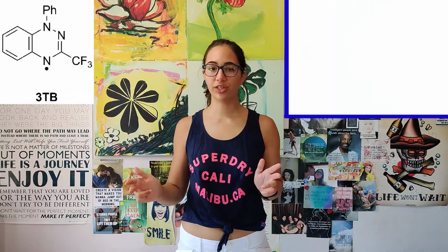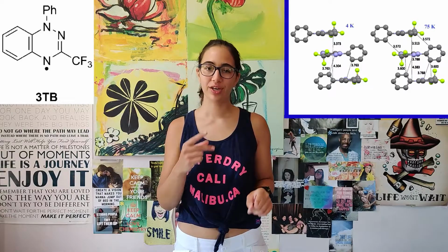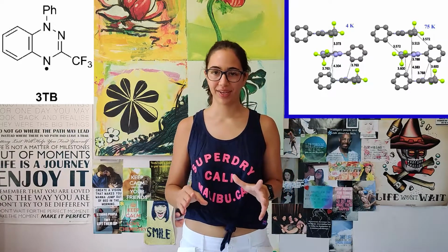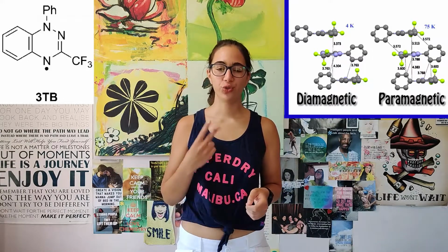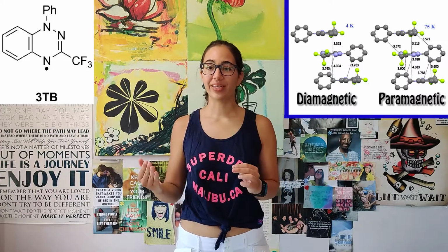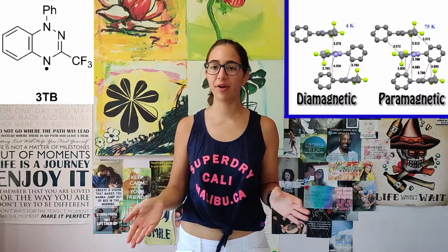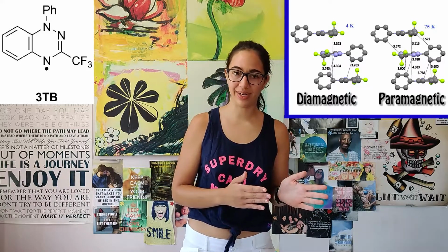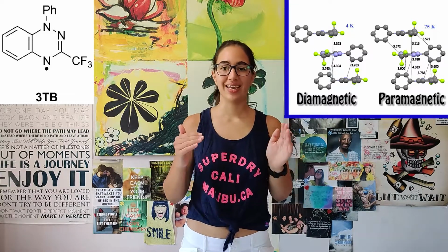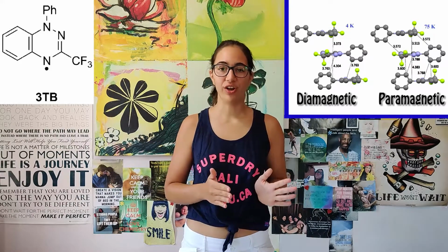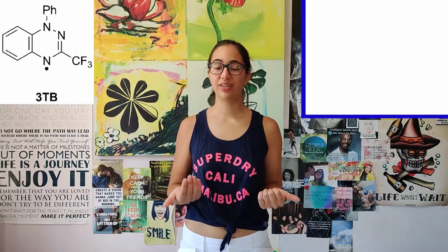The second example is that of a trifluoromethyl Blatter radical derivative, which exhibits a reversible sharp spin transition. The first order transition proceeds via subtle changes of intra and interstack interactions between 2 energetically similar structural phases. The low temperature phase of 5 to 60 degrees Kelvin is diamagnetic, stemming from a multicenter 2-electron interaction. The high temperature phase at 60 to 300 degrees Kelvin, on the other hand, is paramagnetic as a result of non-interacting spins arising from weakly bound dimers. The change in arrangements takes place through slight changes in interplanar distance and degree of slippage along the stacking direction, which are critical to their magnetic properties.